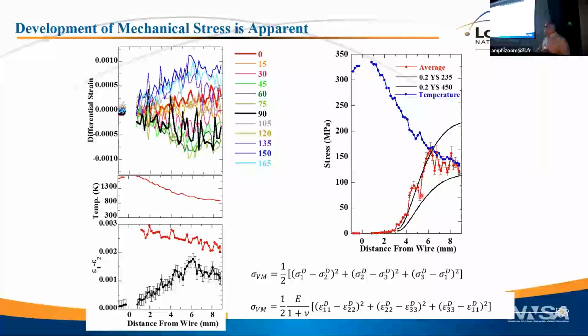Well, the von Mises stress, again, this is the yield criterion. So when the material reaches this stress, it should yield. The fact that it follows in between these bounds quite well says that I'm doing at least a plausible job of calculating a stress that's actually meaningful to the prediction of what's happening in the microstructure. I'm able to see when the material reaches its yield point and the stress saturates, and it can't go up any higher because now it's flowing plastically.